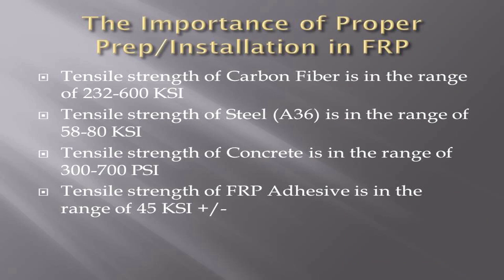Just to further emphasize the importance of proper prep and installation in FRP, as you can see from these numbers, the tensile strength of carbon fiber is high. It's typically 5 to 10 times stronger in tension than your most common structural steels, just A36. So it's a really strong material, but it will never see those strengths because we have this very expensive, very strong material that's only as strong as the glue that's adhering it to that concrete. And the glue is only as strong as how well that substrate's been prepared. If you've got punky concrete, it's going to pull right off. So tensile strength of FRP, not necessarily shear, is around 45 KSI. So you can see that it all comes down to the adhesive and the prep.